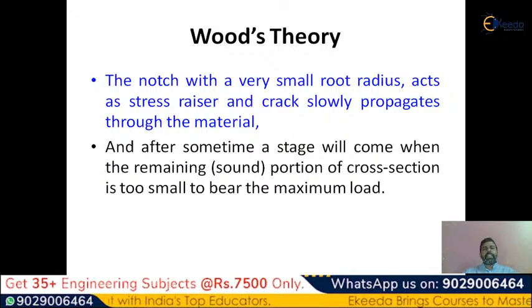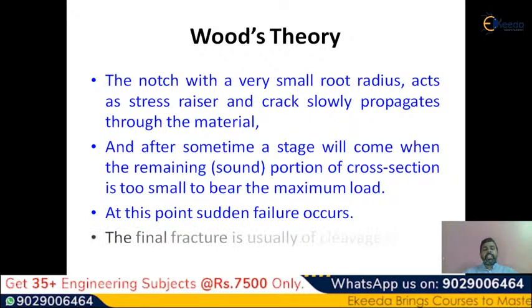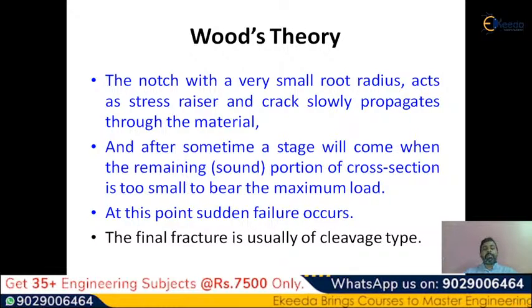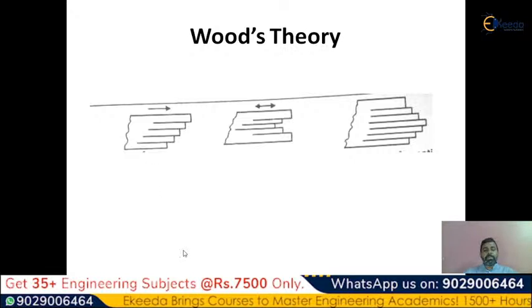If the slip band moves in the forward direction, and again in the backward direction, any material can't withstand that. That's the problem. At this point, the failure may be observed. The final fracture is usually of a cleavage type. You can observe here these slip bands in forward direction and in backward direction, so that means to and fro direction.